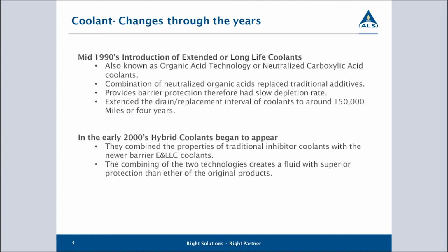Around the mid-90s, we started to see a completely new technology coming into the coolant space, normally referred to as extended or long-life coolants. These were meant to be a fill-for-life type coolant, where instead of a coolant that needed to be re-additized at intervals, it could be put in the system and left to work continuously, typically for the life of the system. The principle these coolants worked on is that instead of using a sacrificial additive or inhibitor, they used a barrier technology. The additives, normally some form of organic acid, would plate out on the metal and prevent oxygen from penetrating the layer and coming into contact with the surface, and this would stop corrosion from taking place.